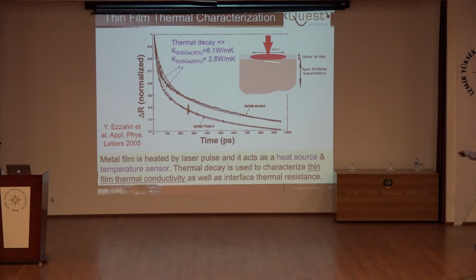Again, it's a bulk material, thin film material sitting on a substrate. I'm interested in thermal conduction perpendicular to the plane. Lasers allow us to do that. You put an aluminum film. Aluminum film absorbs light at 780 nanometer that comes from a Ti-sapphire laser. The laser heats up the surface at time 0.